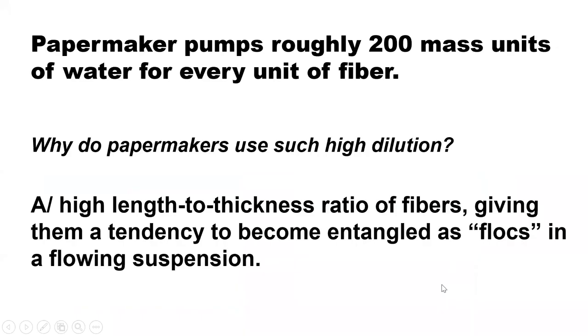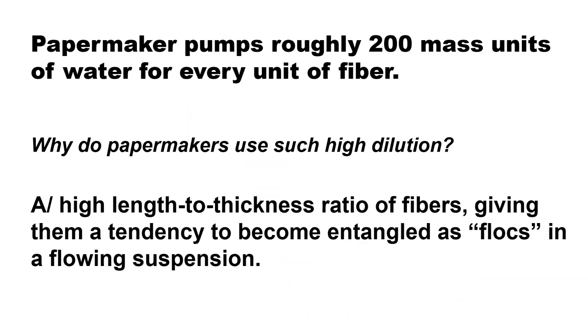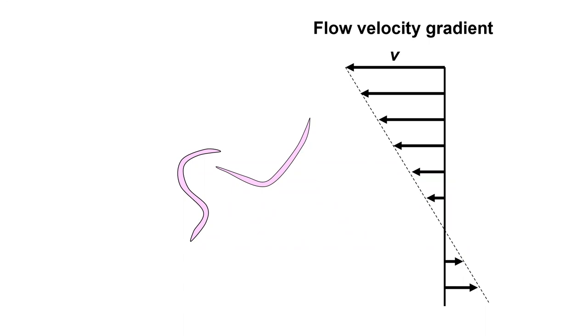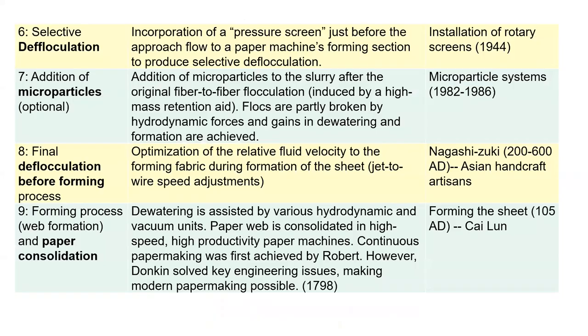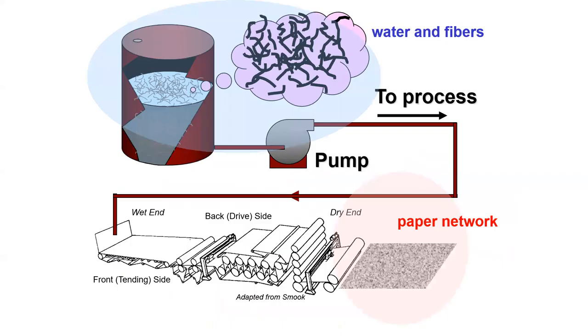Those capillary forces start to happen during the drying section — where there is very little water — the capillary forces are the highest, and the water being evaporated pulls the fibers together. By surface tension and capillary forces, the fibers get closer and develop bonding — very strong hydrogen bonding. We use so much water at the beginning because we want the fibers suspended in water, very well dispersed, forming flocs. When they are mixed with water and in the flow field of the paper machine, fibers find the opportunity to entangle and flocculate. That flocculation we try to improve in the process.